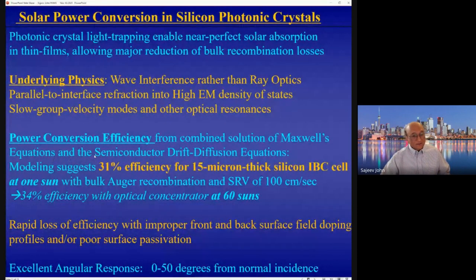The best case that we've considered is a power conversion efficiency obtained by solving the combined Maxwell equations and semiconductor drift diffusion equations, with modeling suggesting up to 31% efficiency with 15 microns of thickness if everything is done ideally. And this is at 1 sun power and a surface recombination velocity of up to 100 centimeters per second. If you use solar concentrators, that can actually increase the efficiency further. With 60 suns, this goes up to 34%.